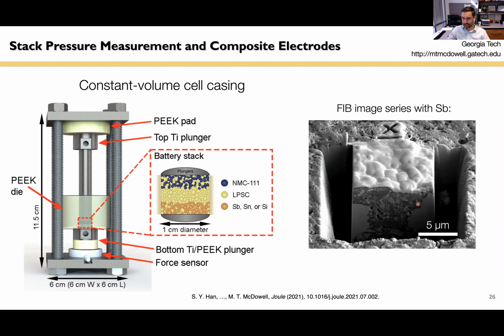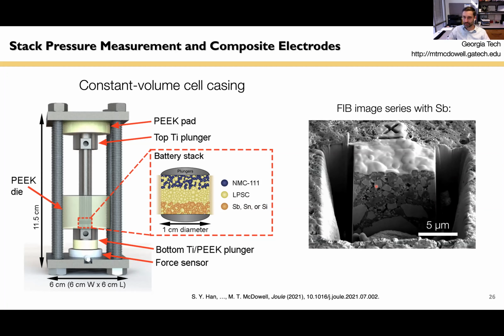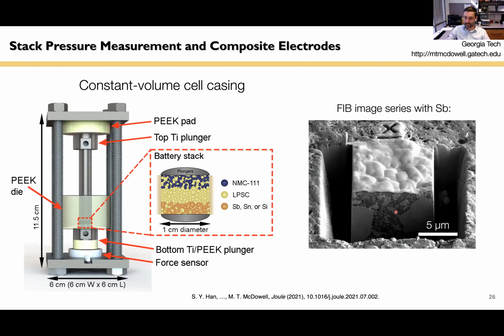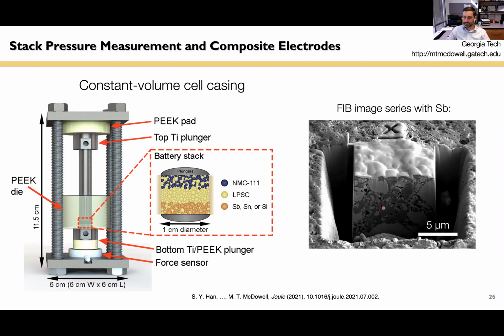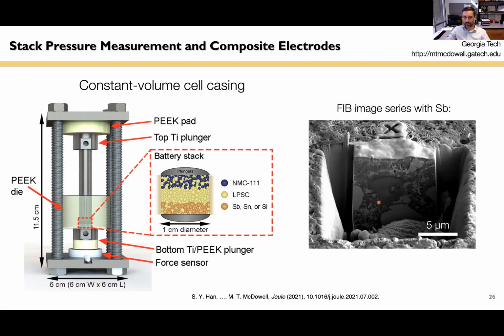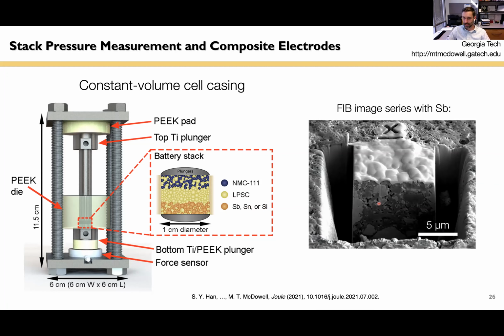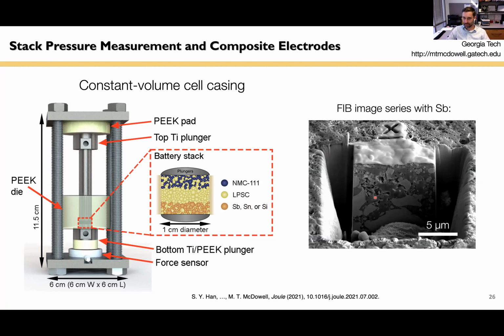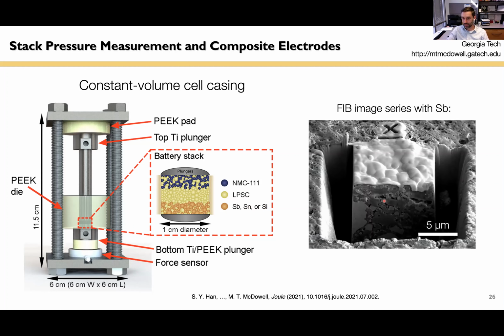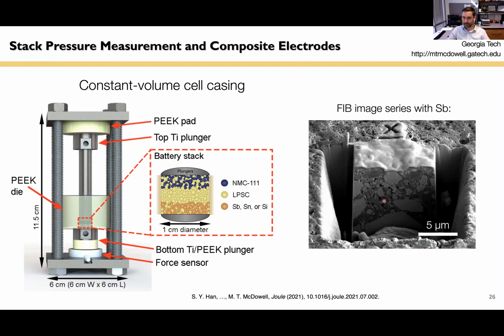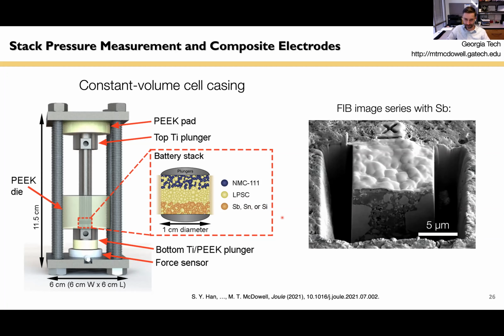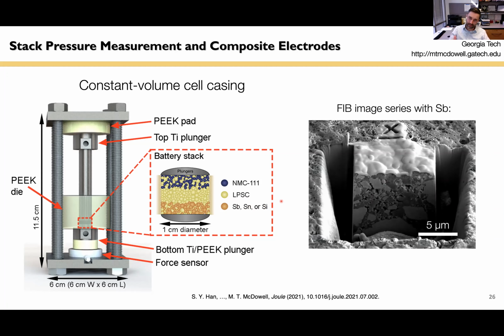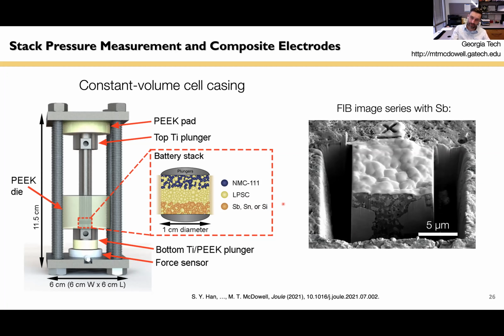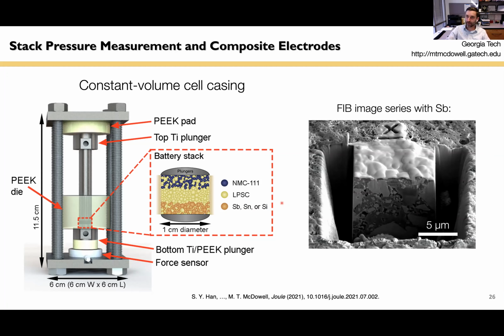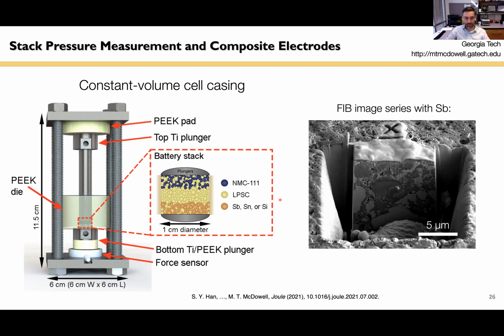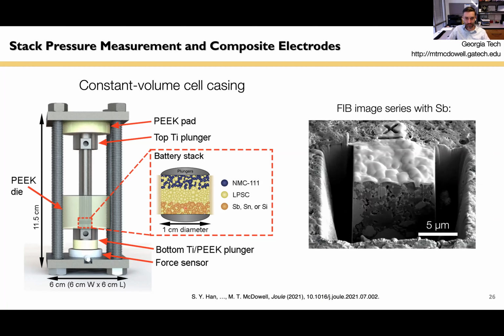But in this data set here, you can see this is the composite structure. The lighter regions are the antimony particles. They're rather large. The darker regions are the mixed in solid electrolyte, which is the argyrodite material. It's a little smaller. And then we also have these black regions, which are pores and voids. So this is really not an optimized structure, actually. We would like to get rid of some of those voids probably. But anyway, the intention here is to understand how, with these interesting electrodes that can show high performance, stack pressure changes with cycling, and how that relates to the materials transformations.